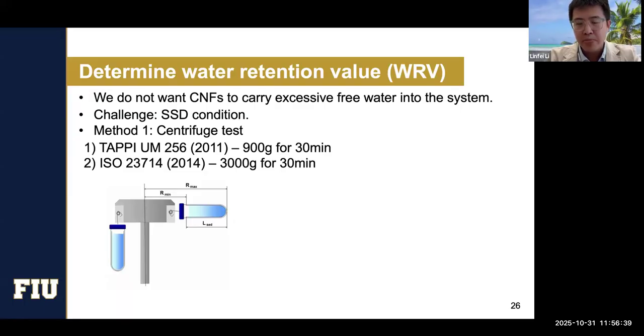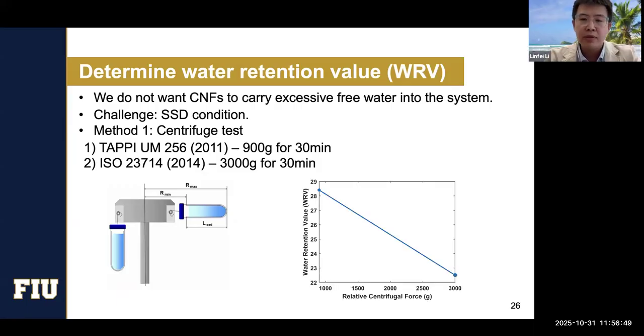So one is TAPPI, which uses 900 G of gravity for 30 minutes. The other one is the international standard, which uses 3000 G for 30 minutes. So we run both of them. For 900 G, the retention value for the CNF is a little bit over 28 grams per gram. And for the 3000 G, it's slightly below 23 grams per gram.